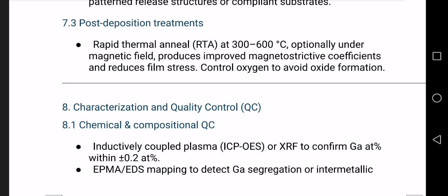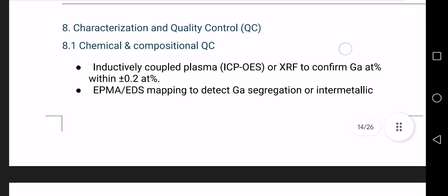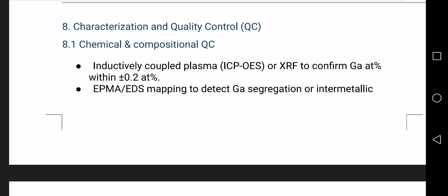Sometimes annealing is done under a magnetic field. This induces preferred magnetic direction, improves low field response, and oxygen control is very important. Okay, because Ga oxidizes easily. Oxides reduce magnetic performance, so annealing is done in vacuum and inert gas. Okay, characterization and quality control.